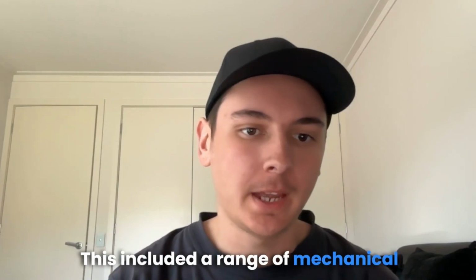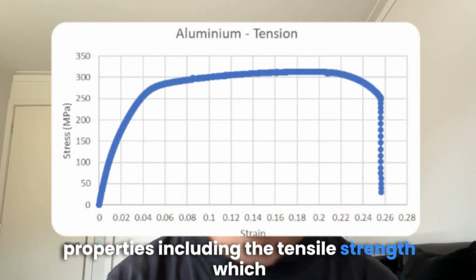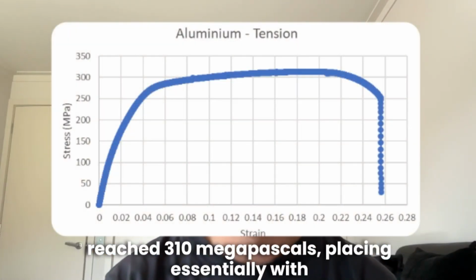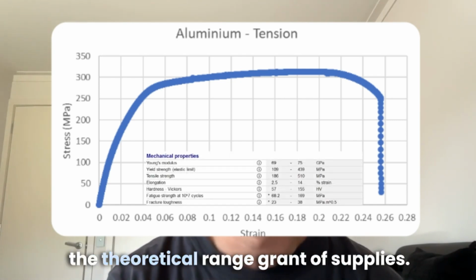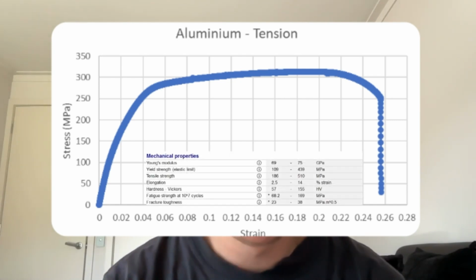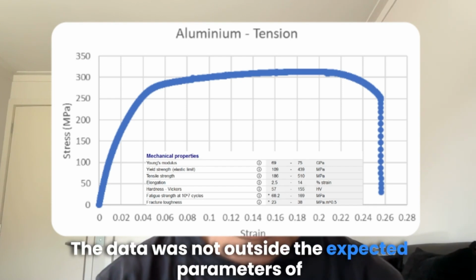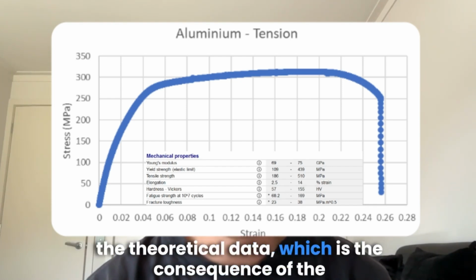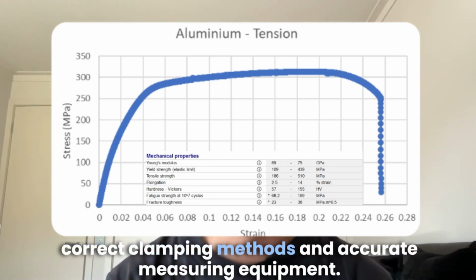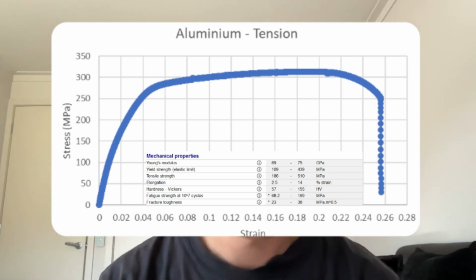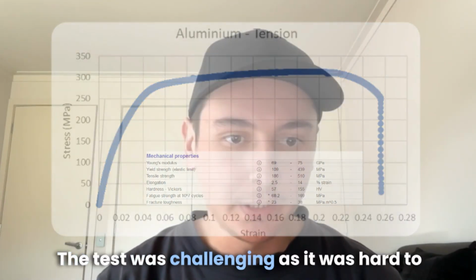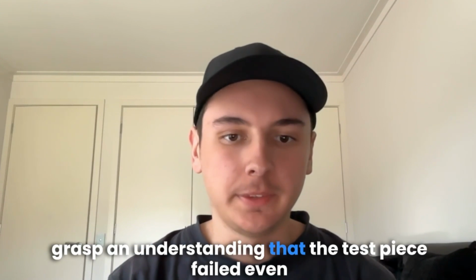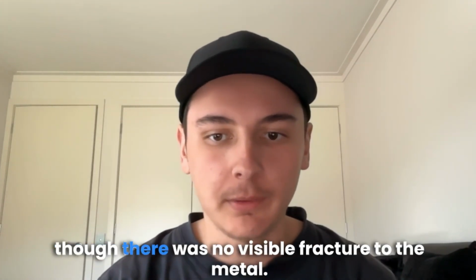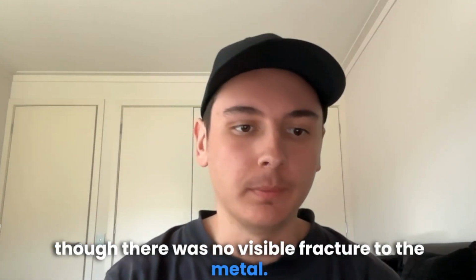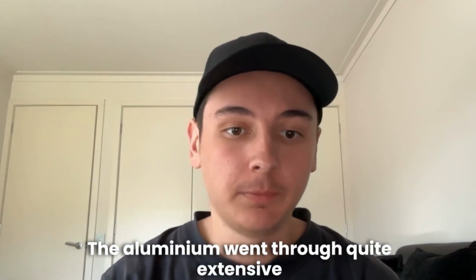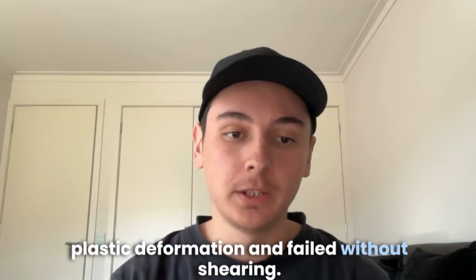This included a range of mechanical properties, including the tensile strength, which reached 310 MPa, placing it centrally within the theoretical range Granta supplies. The data was not outside the expected parameters of the theoretical data, which is the consequence of the correct clamping methods and accurate measuring equipment. The test was challenging as it was hard to grasp that the test piece failed even though there was no visible fracture to the metal. The aluminium went through quite extensive plastic deformation and failed without shearing.